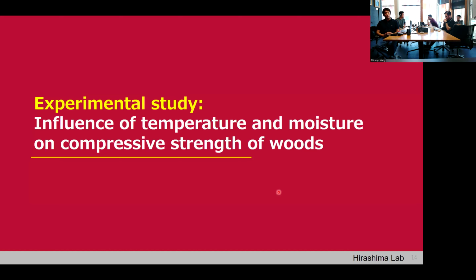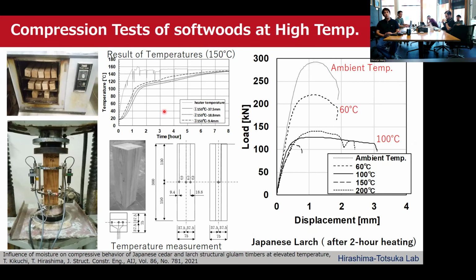Next, I'd like to introduce our experimental study on the influence of temperature and moisture on compressive strength of wood. We investigated the compressive behavior of softwoods at high temperature using a conventional oven and a loading device. The test parameters were temperature and heating time, and we also investigated the weight change due to water evaporation. The test specimen was loaded immediately after heating, and it took approximately 5 minutes to complete the test.